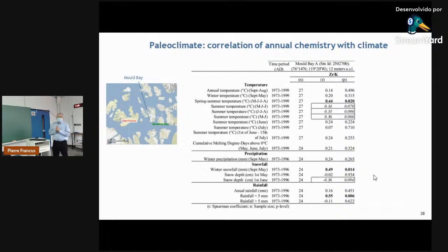Now, what is the most difficult thing to do in the Arctic is to make correlation of what we find in the sediment and the instrumental climatic record. So here at Cape Bounty, the closest weather station is something like 180 kilometers away, and it's also very short. So we have data only for 27 years, from 1973 to 1999. And so basically what you look at is different temperature indices or precipitation indices or rainfall or snowfall, and you try to correlate the value of the zirconium to potassium ratio measured with the ITRAX for year 1999, then 1998, and so forth. And you come up still with interesting correlations, at least in earth science. This is something that is quite good.